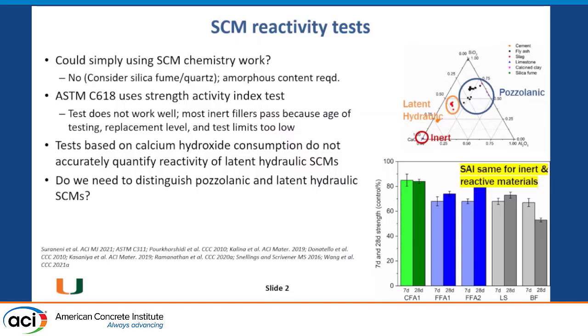Do we need to distinguish pozzolanic and latent hydraulic SCMs? Well, as I mentioned, these materials have different effects on durability and different replacement levels, so it could be important to distinguish them. But the reality is that if something has less than 15 or 20 percent calcium, it's not going to be latent hydraulic. So, just the calcium content could be a distinguisher. Whether you need to distinguish total reactivity versus pozzolanic reactivity depends on what you want, but this is not a particularly hard distinction to make.